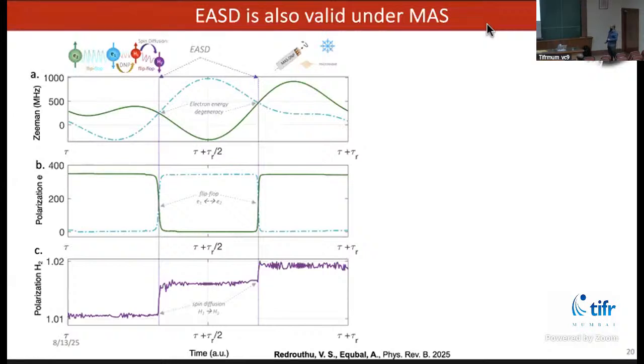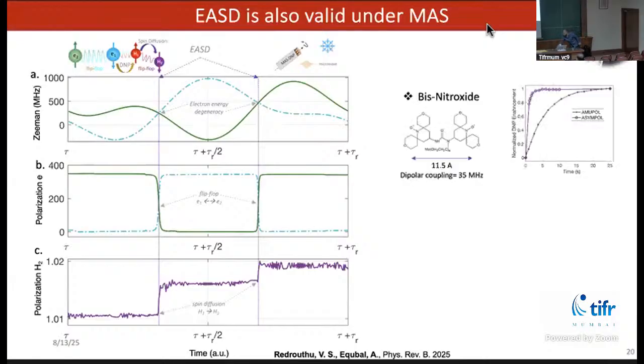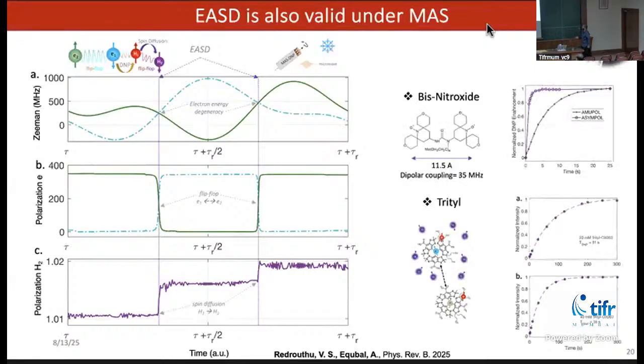So far I have shown theoretical stuff, but the principle is also valid experimentally, which is tested here. When we compare biradicals with two different distances, a biradical which has shorter distance or stronger coupling leads to faster buildup. And even for monoradicals, if we concentrate the radicals such that the average distance is shorter, then the buildup time becomes faster.